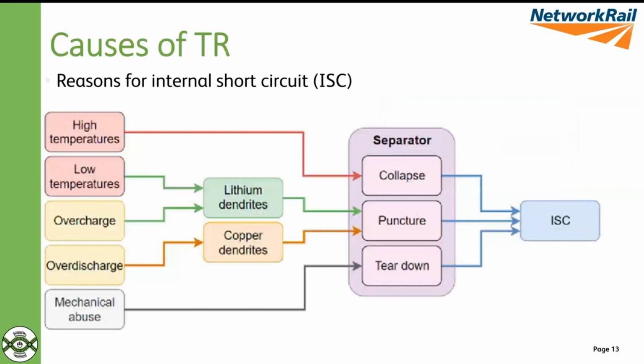However, in more serious cases, you can get things called dendrites forming, and these are microscopic structures that form out from the anode, and they can form all the way to the separator, and they can puncture the separator. And once you lose separation between the two electrodes, the cathode and the anode, you end up with a short circuit and a fire.